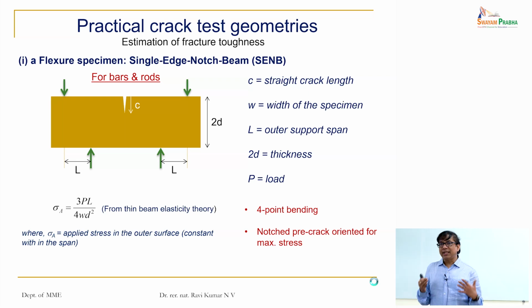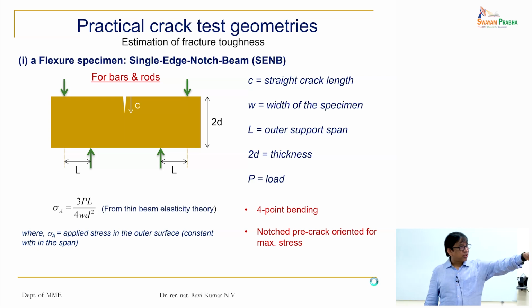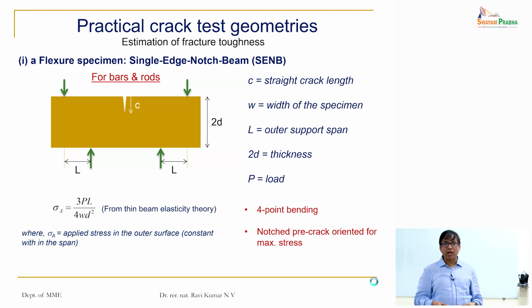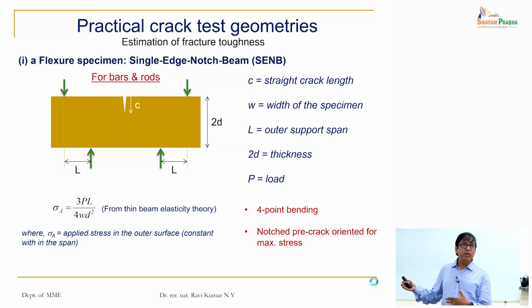One of the important testing techniques that we use in ceramics is to determine the fracture toughness. For example, glass has a fracture toughness of less than 1 MPa root meter. If I throw a stone at it, the glass will break because it has a fracture toughness of 0.5, 0.7, 0.8 MPa root meter, and so it's extremely brittle. A metal has a fracture toughness of more than 50 MPa root meter. Ceramics typically have a fracture toughness anything between 1 or 2 MPa root meter to around 15 or 20 MPa root meter. A highly tough ceramic microstructure may have a fracture toughness of around 15 to 20 MPa root meter. The dream of any ceramic scientist is always to improve the fracture toughness. How do I improve the fracture toughness so that it can have real-time application?